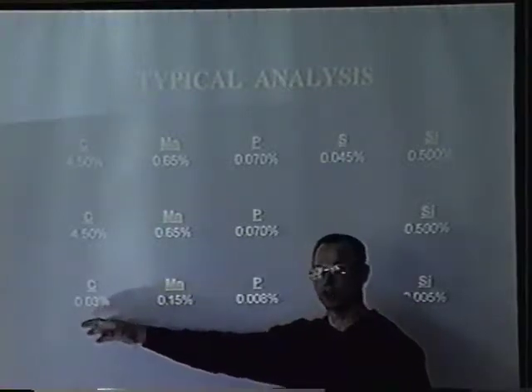There's a 0.03 to 0.06 carbon. A lot of our plate customers are up in the 0.12 to 0.2 carbon range. We've knocked the manganese out. The manganese oxidizes also along with the carbon. It goes out in the form of a gas.